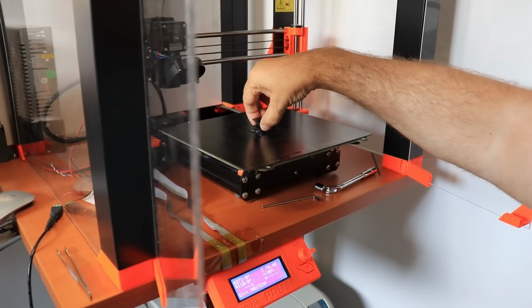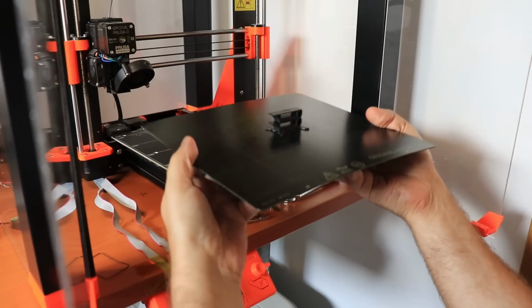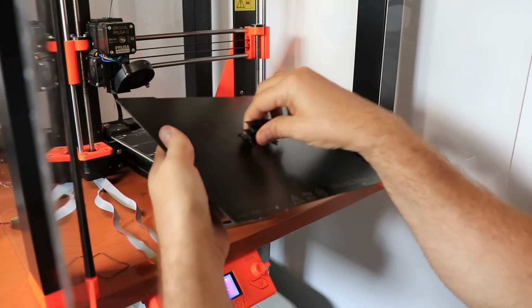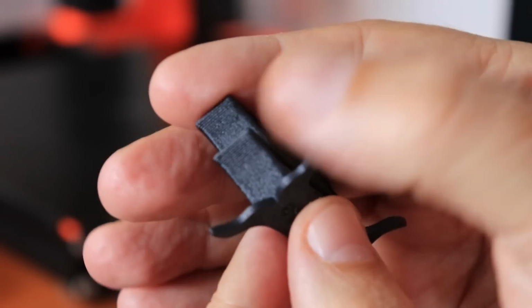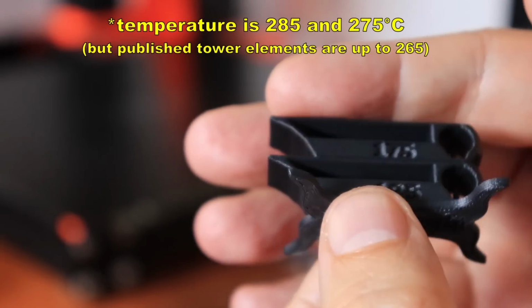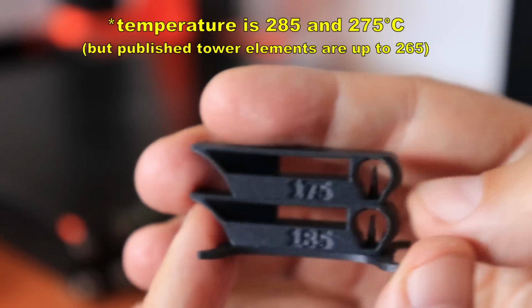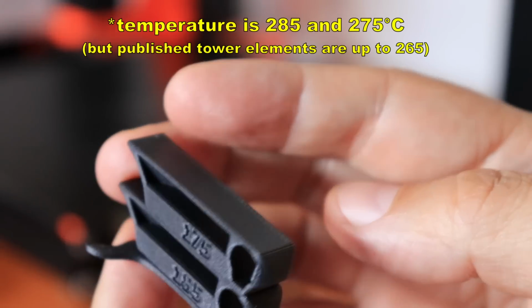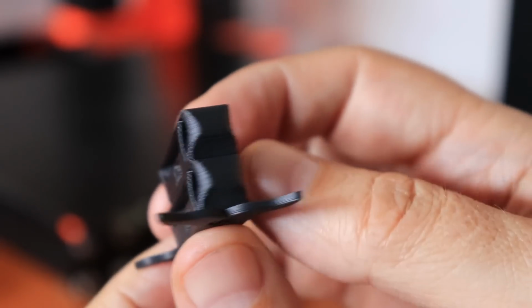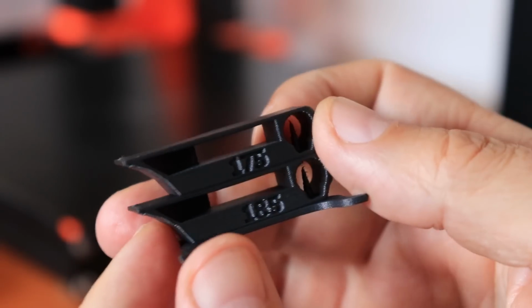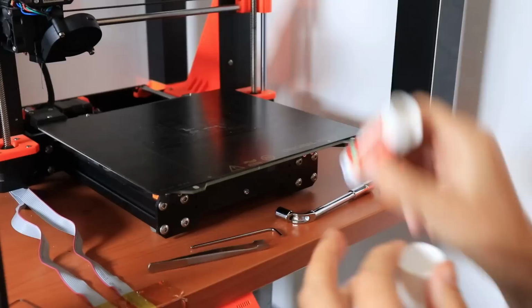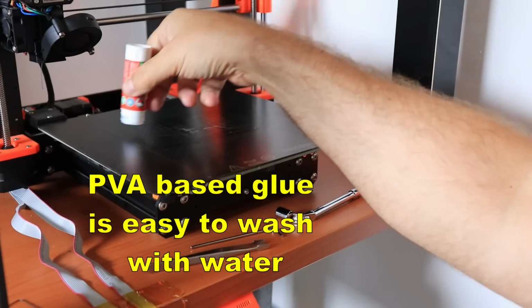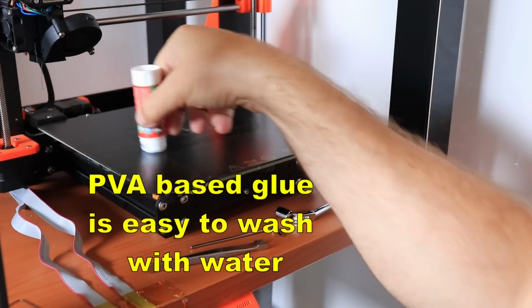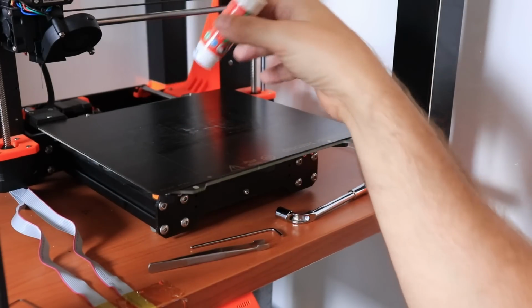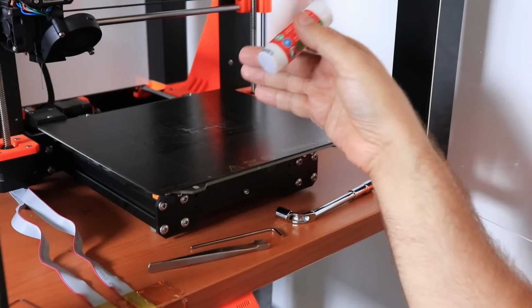Printing is finished, and immediately I want to check the bed adhesion, which looks great. Look at this perfect overhang, perfect bridging, absolutely no problems with this surface. I will not even remove this glue stick, I will just add another layer because now the printing surface will be a little bit bigger, and I will print all test objects at once.